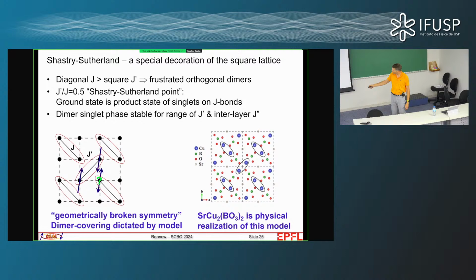What you can do is you can take such a square lattice, you put a spin on each site in such a square lattice. But now, in addition to just having couplings along here, we put also some coupling along the diagonals in such a crisscross pattern as this one here. And if this coupling J here is much larger than the coupling J prime, then essentially each of these diagonal bonds will form a singlet. And the ground state of this model, which was invented by two theorists, Shastry and Sutherland, would simply be a product state of a singlet on each of these bonds here. So fairly well defined and easy to work with ground state. So in fact, this is one of the few models in 2 dimensions that has an exact known ground state, as long as J is much larger than J prime.